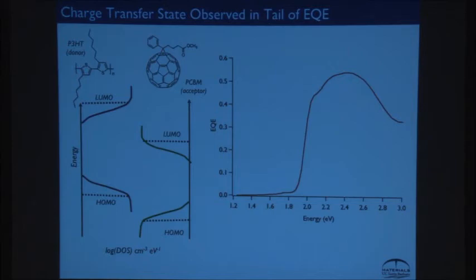What I didn't mention is, some of these polymers, when people use the solvents when they cast them, there's evidence that the polymers pre-aggregate as they're being spun cast. And so people add mixed solvents to try to control that process a bit. And then once it's cast, there are endless hoops people jump through to add solvents to get it to mix and so forth. In this particular system, you don't really need to do it because it's so mobile. This stuff doesn't aggregate that much. It's not very stiff, so it's not quite like a coil polymer, but it's close.